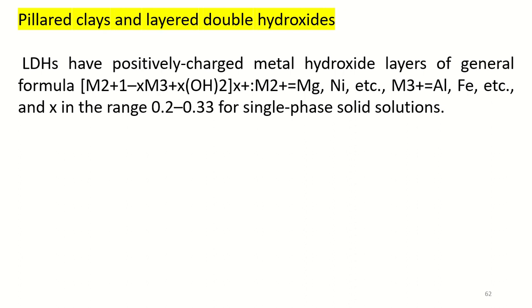LDHs, the layered double hydroxide compounds, have positively charged metal hydroxide layers of general formula [M2+(1-x) M3+x (OH)2]x+, while the metal 2+ may be magnesium or nickel, etc., and in the case of metal 3+, it may be aluminium 3+, iron 3+, etc. And x is in the range of 0.2 to 0.33 for single phase solid solutions.